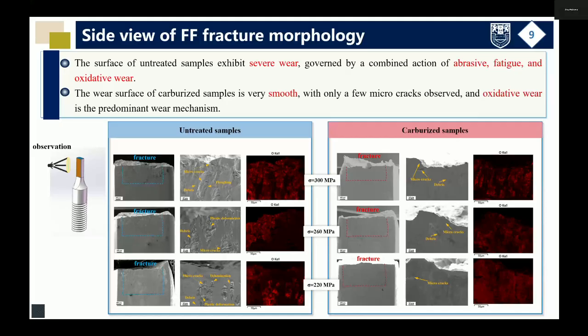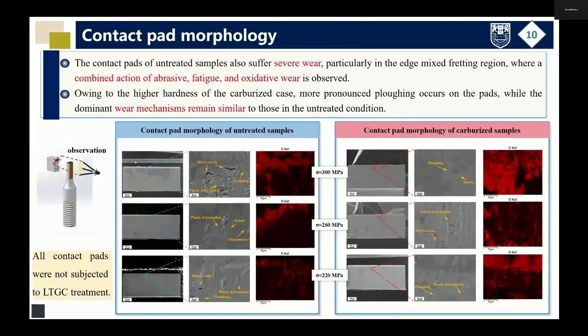The wear surface of the carburized sample is very smooth because LTGC forms a much harder surface on 316L stainless steel. Only a few microcracks are observed, and oxidative wear is the predominant wear mechanism.